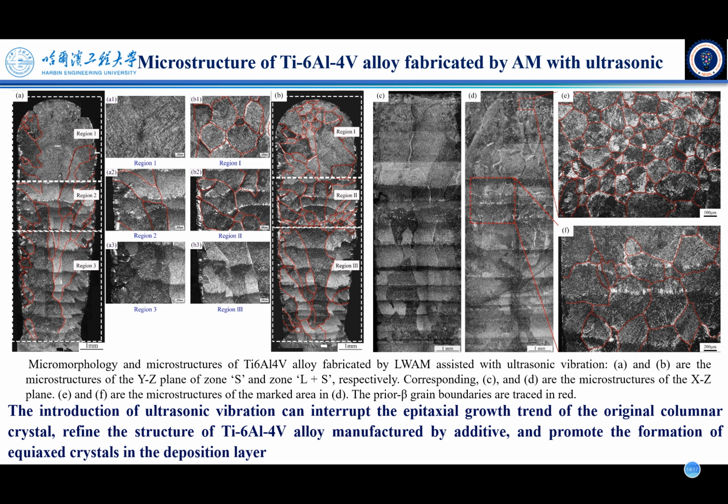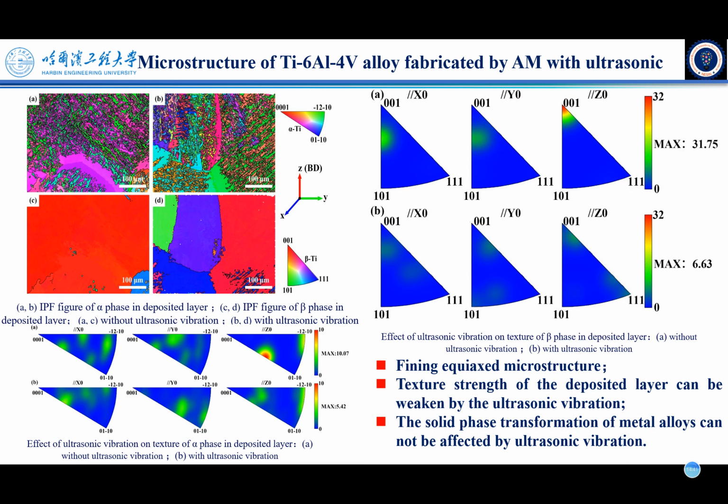The introduction of ultrasonic vibration can interrupt the epitaxial growth trend of the original columnar crystal, refine the structure of titanium alloy manufactured by additive manufacturing, and promote the formation of equiaxed crystals in the deposit layer. Finding an equiaxed microstructure, the texture strength of the deposit layer can be weakened by the